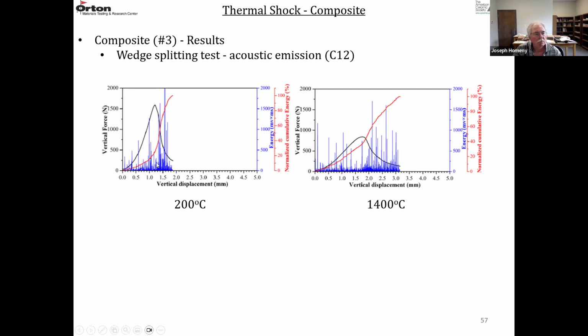So each blue peak is a fracture. The higher the peak, the more energy is absorbed. And then the red is the cumulative energy, and the black is the wedge splitting test. So the black is a load displacement curve. So you can see the wedge splitting shape changes at 1400 degrees C relative to 200 degrees C. A lower peak, more ductile material, and a longer tail. This is about somewhere between 1.5 and 2 millimeter displacement. This is somewhere between 3 and 3.5.